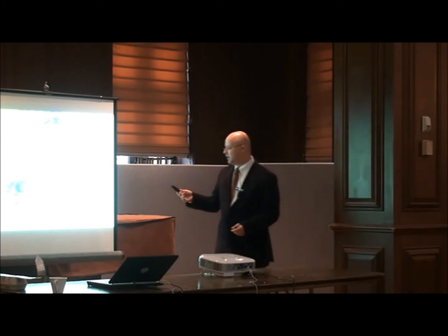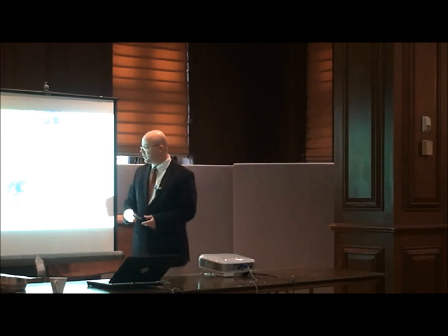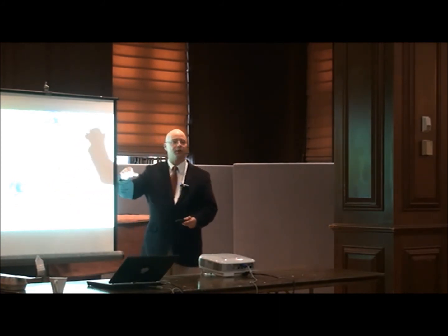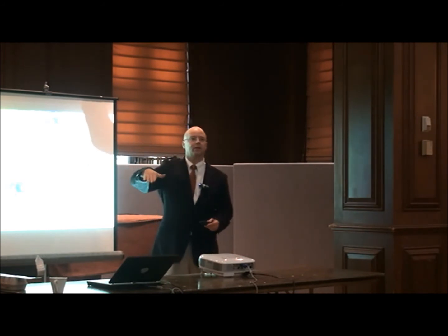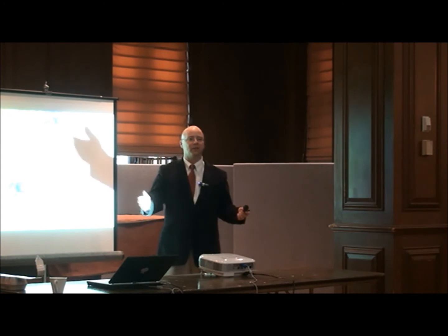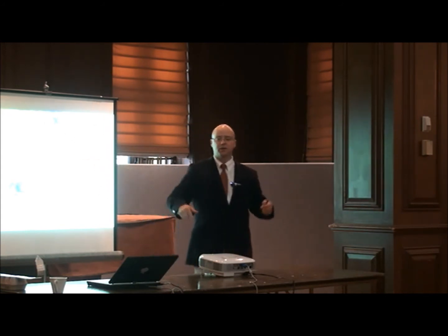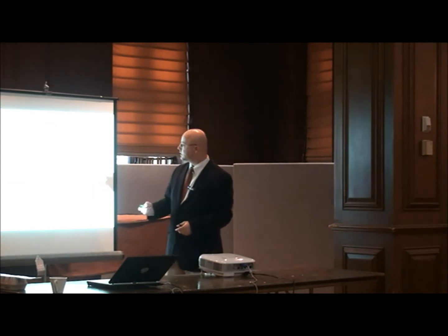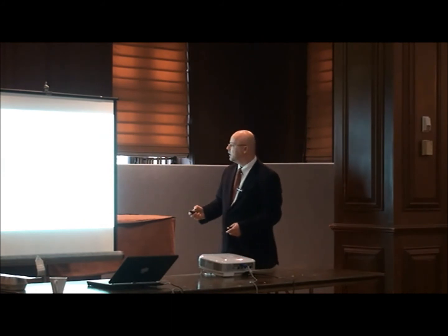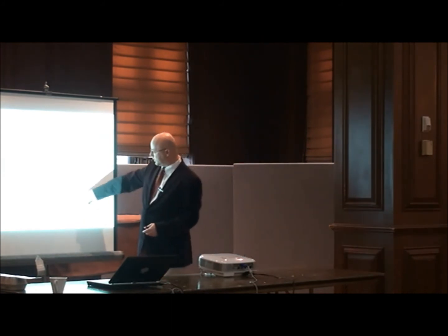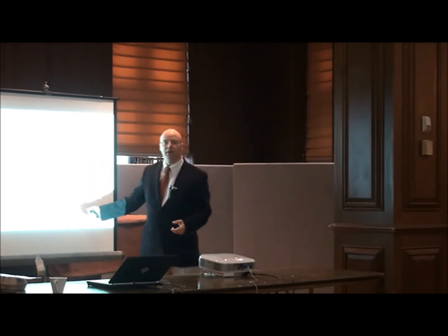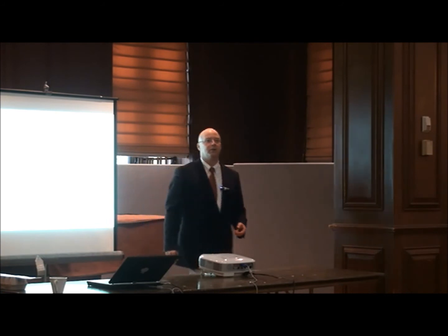So the algorithm we developed for the work with the anthropologists only took measured points. And we figured out that if we did 18 directions on the surface in one quadrant, we would decrease the sampling interval by a factor of 10. So you have to limit now the smallest scale. When you do the length scale analysis on those profiles, the smallest scale that we can go to in order to have comparable numbers with each other is 10 times whatever the minimum spacing was between the points that you measured.